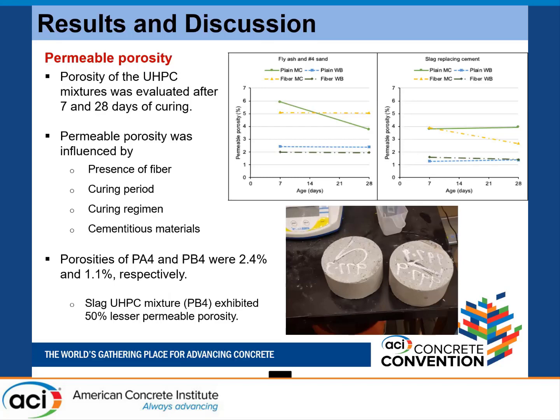Primarily, the presence of fibers, curing period, type of curing regimen, and cementitious materials are the main factors that can influence the porosity. For both these systems, the fibers are constant at 2% by volume. Curing period is the same. Type of curing regimen is the same. But the slag mixes exhibited 50% lesser porosity, which is nothing but the filler effect of the slag that helped the reduction of porosity. This is one benefit we have observed.